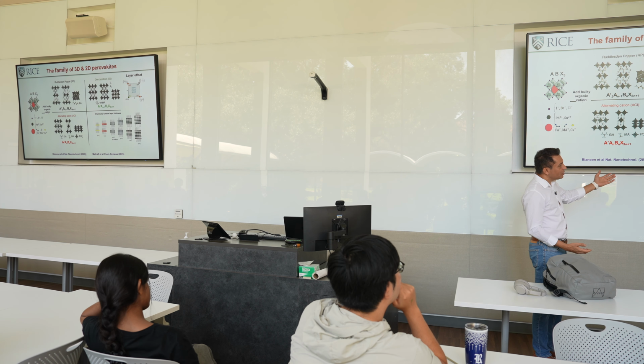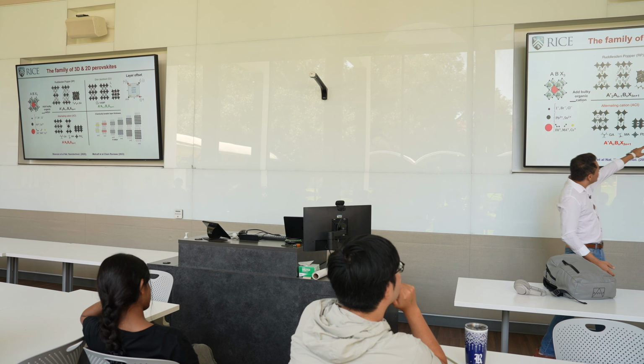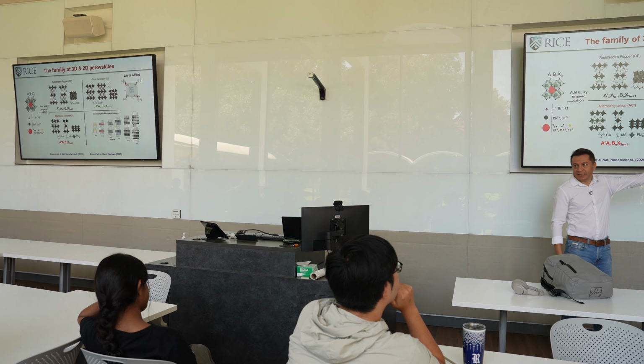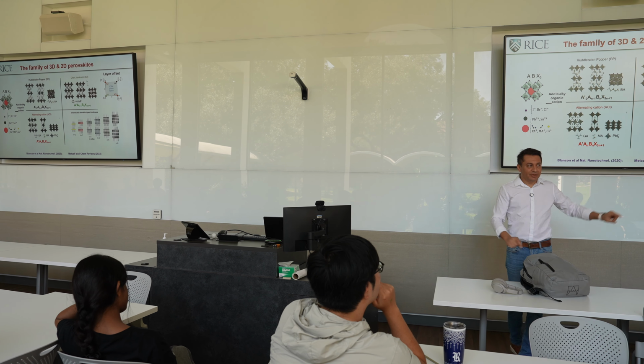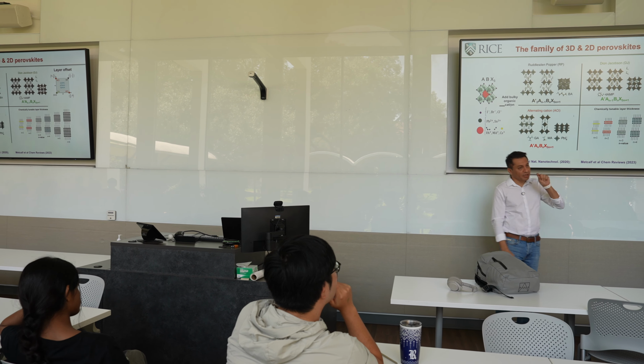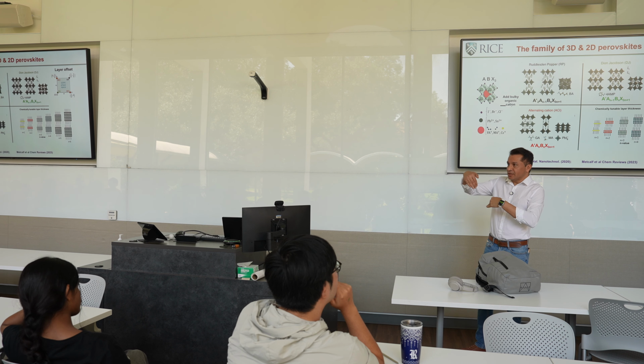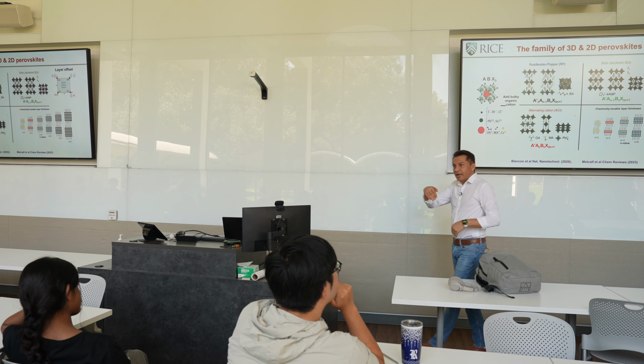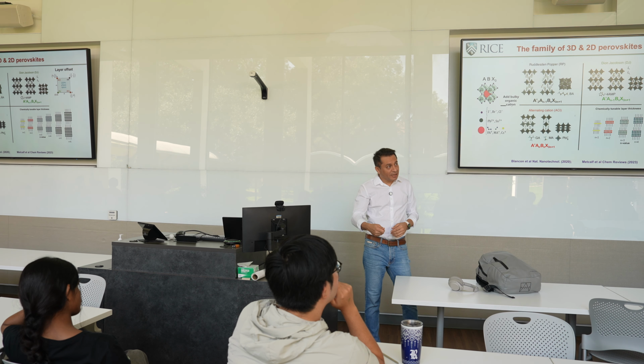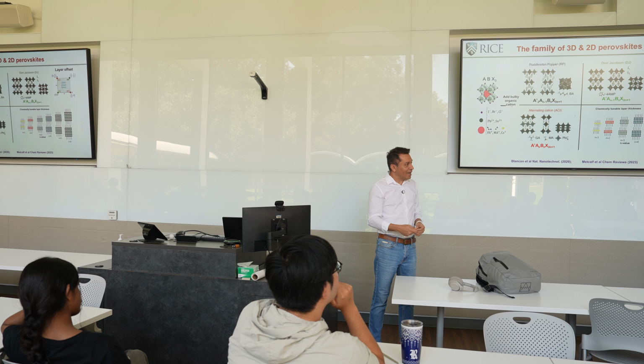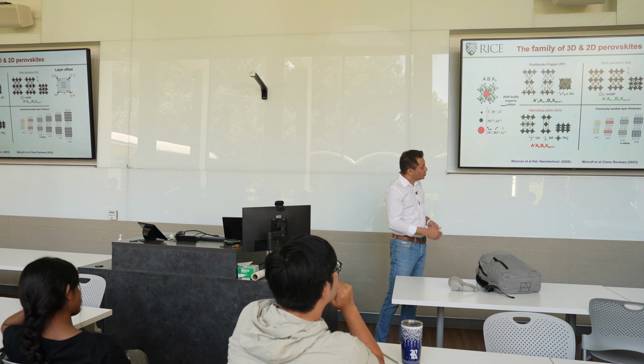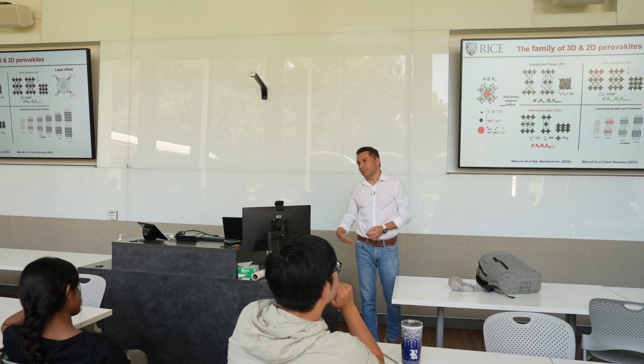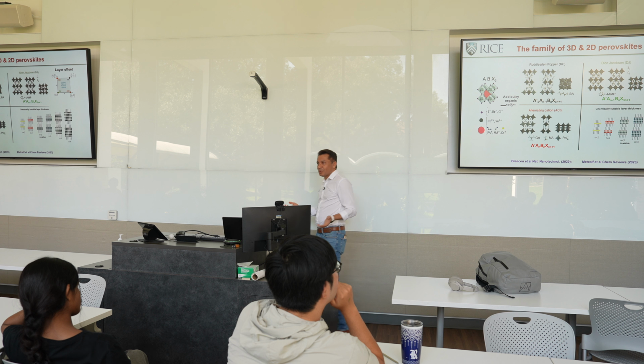You can tune the chemistry, so I can change the number of layers, right? You can see N1, which is just a single layer of the perovskite with a spacer cation. I can keep going and control that chemistry very well in the lab. So I can get 2 layers and 3 layers and 4 layers. And obviously, as physics students, this is perfectly like a particle in a box, right? You're changing the quantum confinement, and so you start to see those changes.